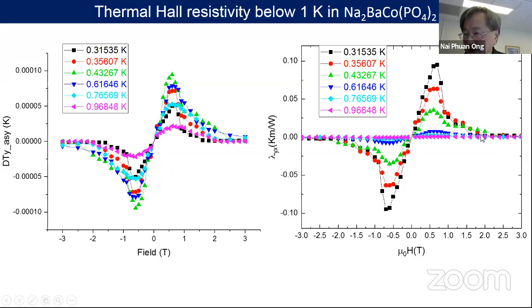So that's why showing the thermal Hall resistivity is a much more honest way to tell the audience or the reader what your noise limits are, what your resolution is, right? So if you look at thermal Hall conductivity, be a little bit cautious, right? Because if the authors have not reported the thermal Hall resistivity, there's no way for you to judge how reliable the measurements are.